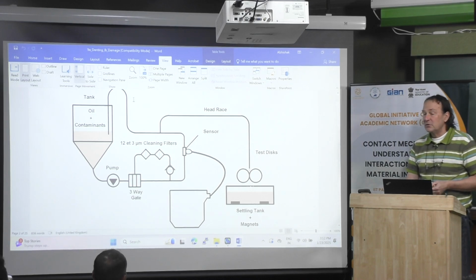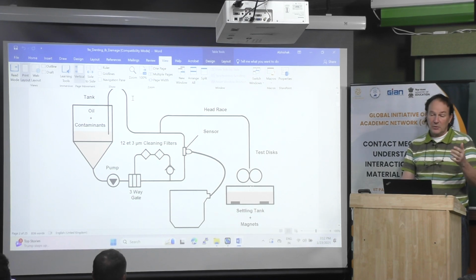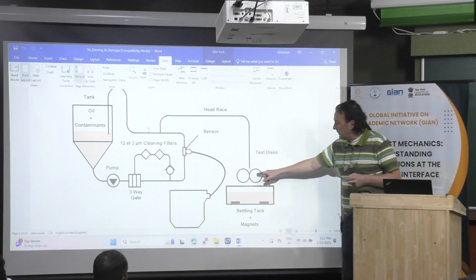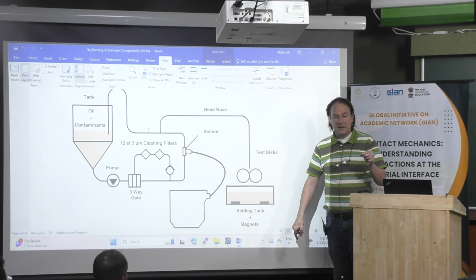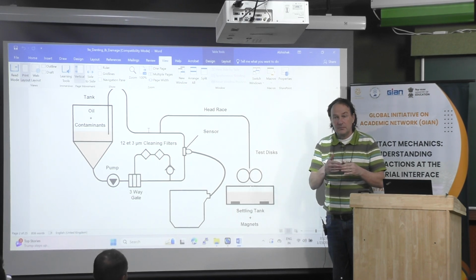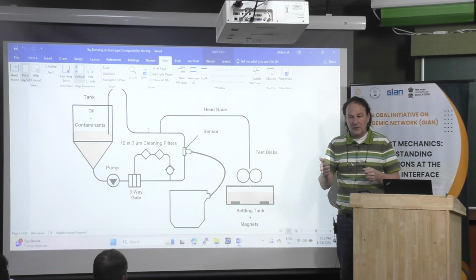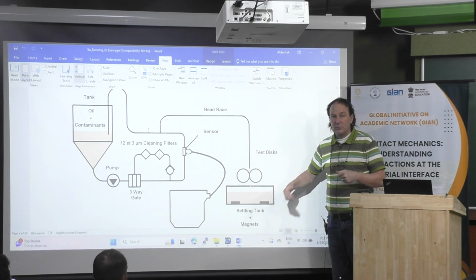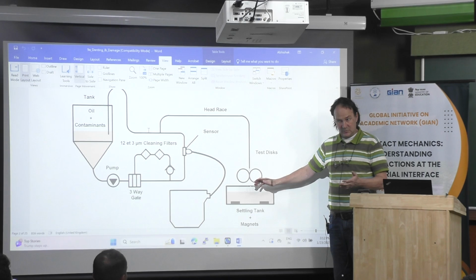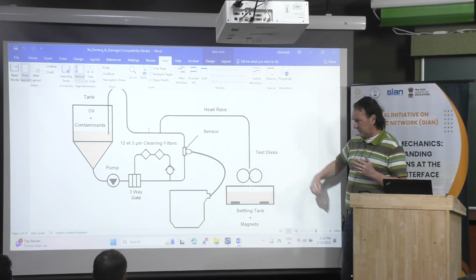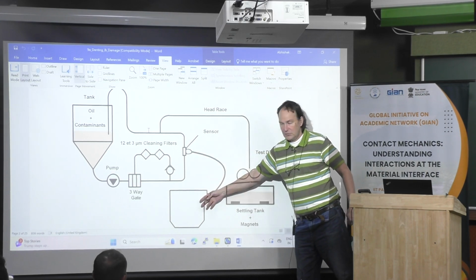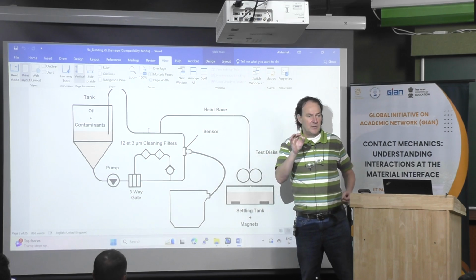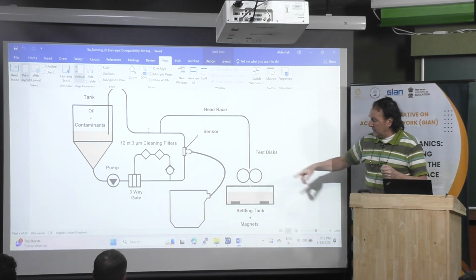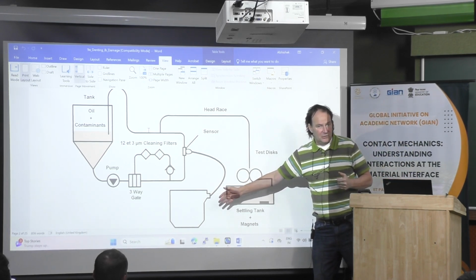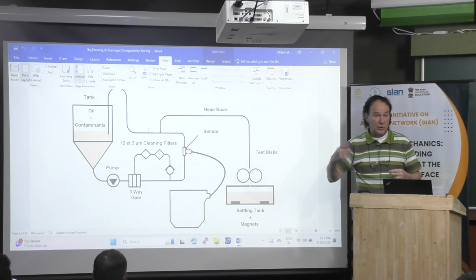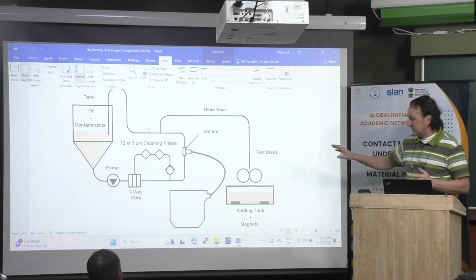Knowing the number of particles per liter, for example, and knowing the flow you have here, knowing also between the two rollers the film thickness and the speed, you can calculate the oil flow. If you know, for example, that you have 1 particle per liter, if the oil flow is 1 liter per minute, you should have 1 particle per minute coming to the contact. This is the principle. To be sure that you have the correct number of particles, you have a particle counter here, and it counts. There is a small derivation, and it counts particles one by one. This is an optical sensor. This type of device is now used on some aircraft engines, jet engines, and they monitor online during flight the number of particles. This is the principle that we developed.